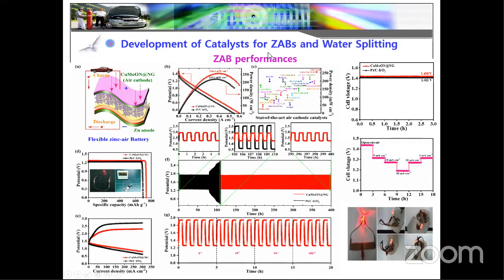Based on the three trifunctional performances, we want to fabricate two different devices. One is a zinc air battery, another one is a water splitting device. First, I fabricated our electrode to act as an air cathode, and zinc acts as the anode. Finally, our fabricated electrodes achieve a higher power density compared to the conventional, and that power density is higher than the recently reported materials.